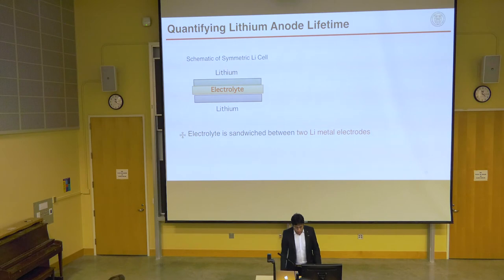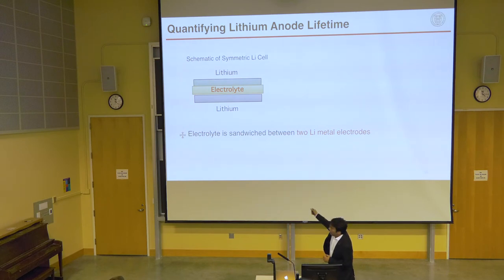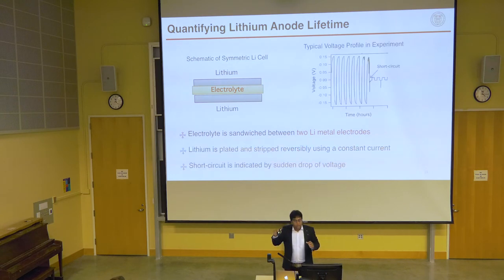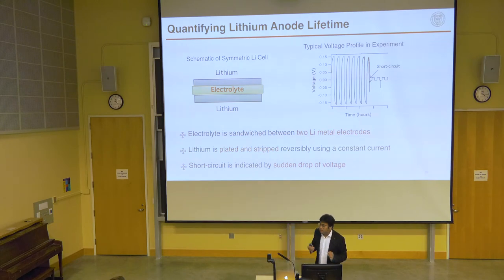So now, to test the hypothesis of whether this nanostructure membrane prevents dendrites, we designed a simple experimental setup. This is a symmetric lithium cell, where both electrodes are made of lithium, and you can see your favorite electrolyte in the middle. In this experiment, we charge and discharge the battery over and over again at a constant current density,